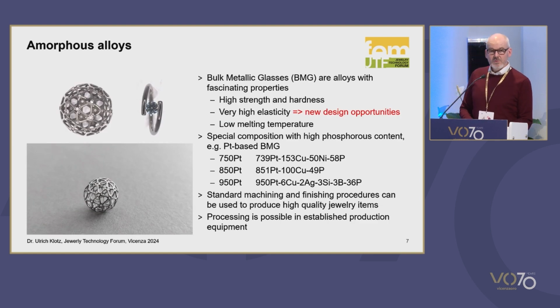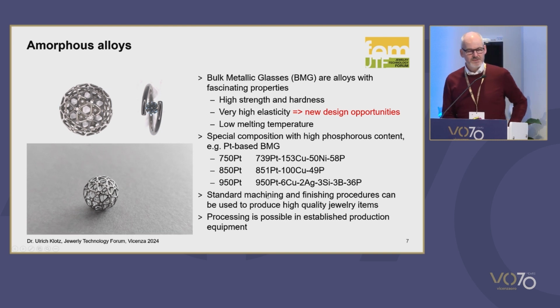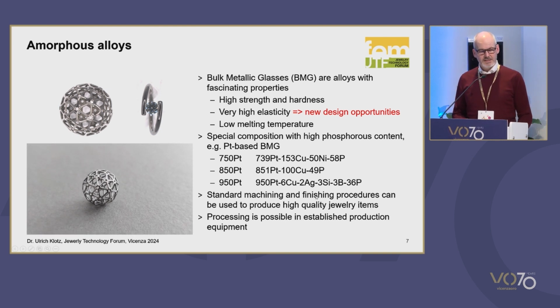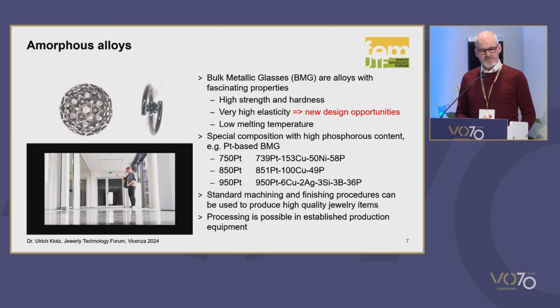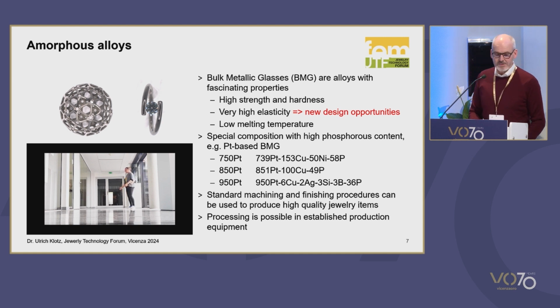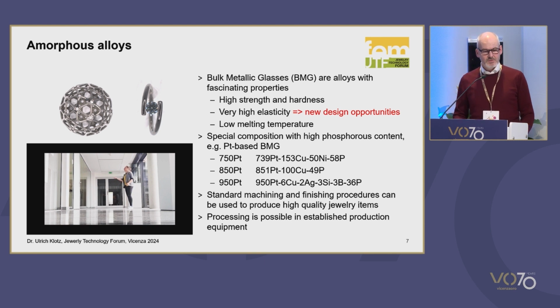Then here is a little movie, the lower image. Maybe you can play this, please. So this is something I presented last year. This is a bulk metallic glass, a platinum-based alloy, which has extremely high elasticity. So you're seeing my colleague Lisa, she's dropping this ball and it bounces back like a rubber ball. And that's because of the very high elasticity of these alloys, and that is very different from conventional alloys.